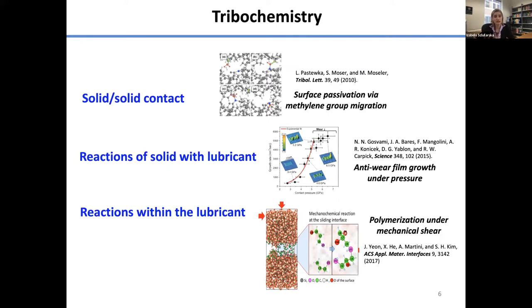There are broadly speaking three types of these chemical couplings. One of them is for solid-solid contacts. An example would be formation of chemically passivating species during sliding of DLC on DLC, diamond-like carbon, so a dry contact. We can have reactions of a solid with a lubricant, so the development of a tribofilm, or reactions within the lubricant, like polymerization of molecules under shear. So they're all important for tribology.